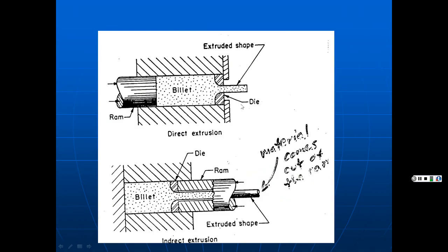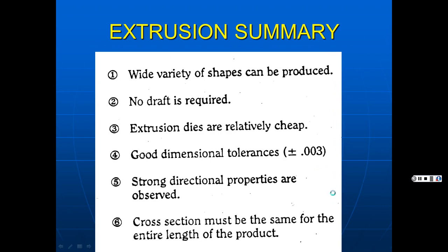Here there's direct extrusion, where the ram squeezes it and it comes out the die opening, and that's what you get here with the indirect, where the ram squeezes it, then it comes out the backside of the ram. So, a wide variety of shapes can be produced. No draft angle is required. Extrusion dies are relatively cheap. Good dimensional tolerances, 0.003 of an inch, plus or minus. Strong directional properties as you're squeezing it through, so the material is pretty strong when you're through. The cross-section must be the same for the entire length of the product, so it's a nice way of making it.